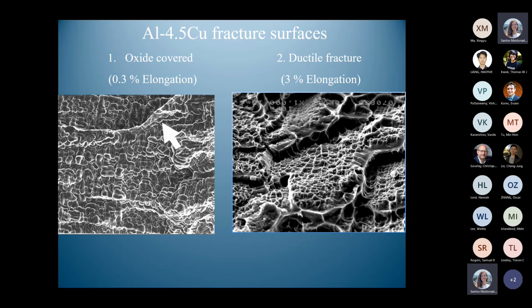What you don't know is you're looking at a bifilm there. And so you remember how that formed with the two lots of dendrites growing either side. Now, the fracture goes through the center. And so now we have, I need more hands to do this, we have two fracture surfaces with dendrites just underneath the surface. And we are seeing those dendrites through the oxide film, which is so thin, you don't know it's there. Which is why we think we've never seen bifilms. Nearly every one of you would have seen bifilms without knowing it. And this is an occasion. There's a little part there, you just see it, where the bifilm is actually folded over twice. And that tells you you're looking at a film.